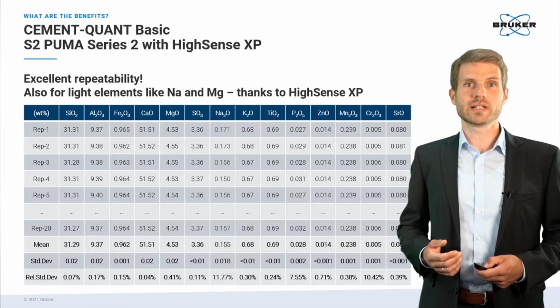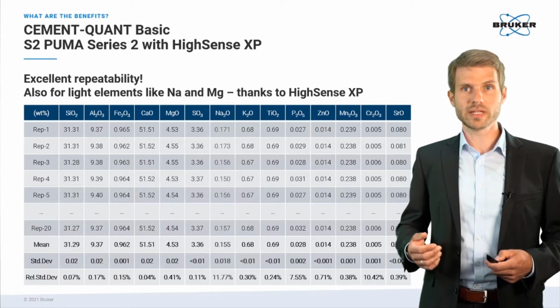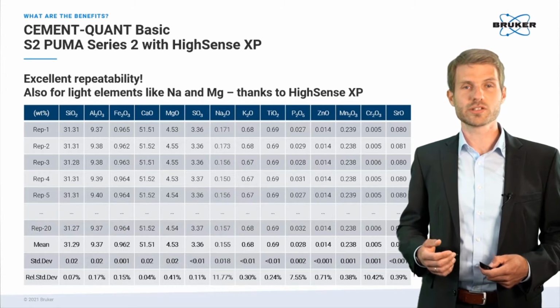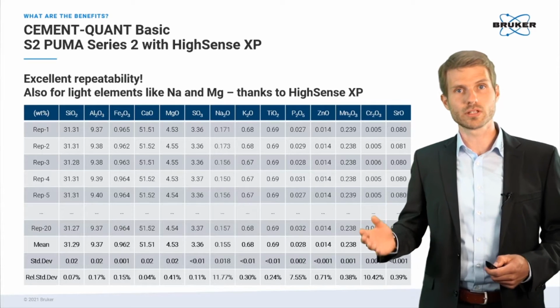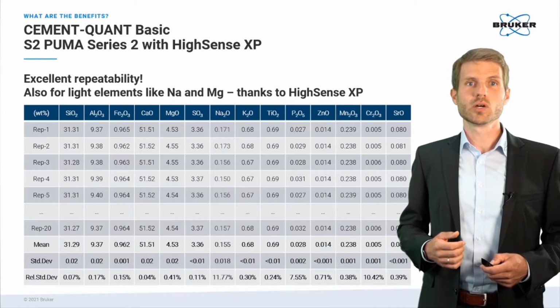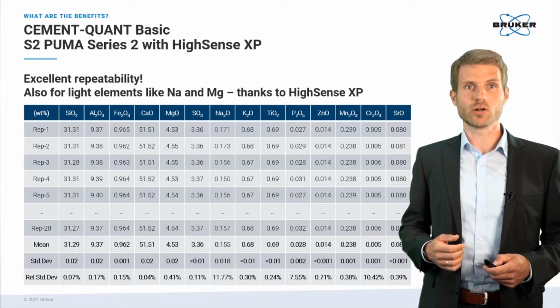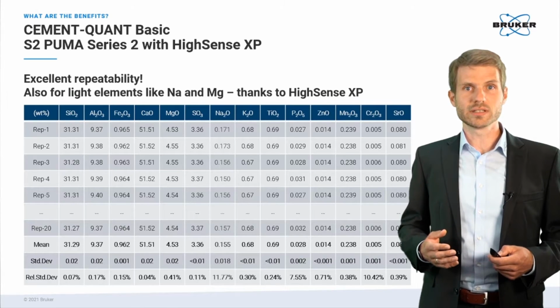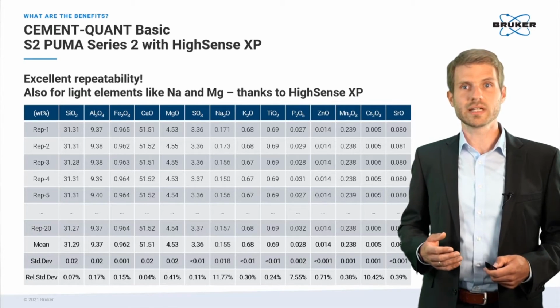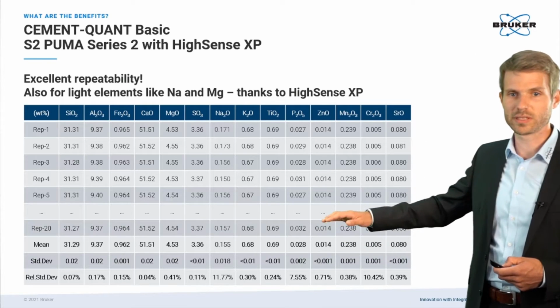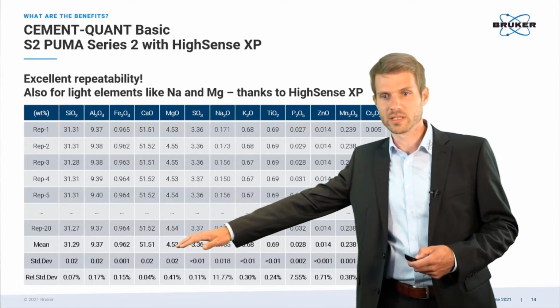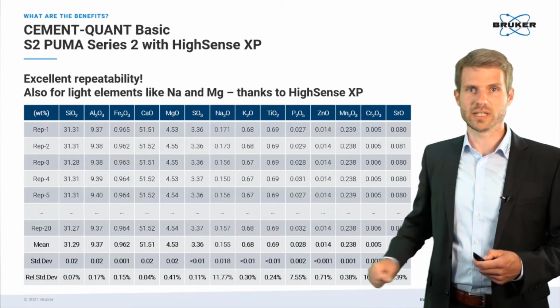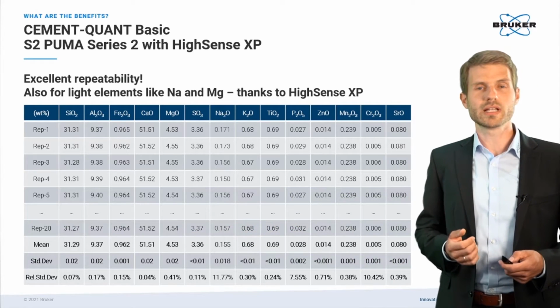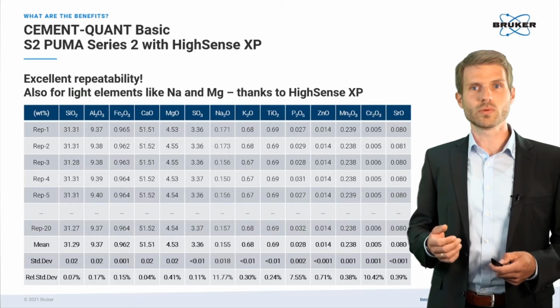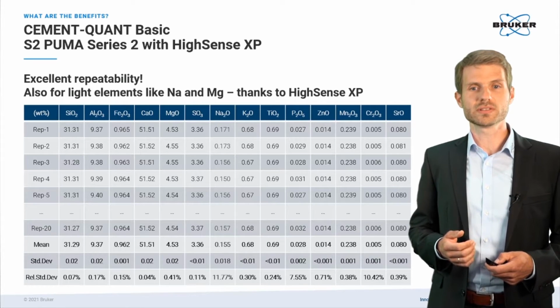Here I show the results of a repetition test where a cement quality check sample was measured 20 times. The sample was loaded and unloaded automatically between the measurements using our XY auto changer. As you can see, we obtained an excellent standard deviation with the S2 PUMA and the new detector. This is particularly visible here from the standard deviations and the relative standard deviations. For most of the elements, the relative standard deviation is quite well below 1%.